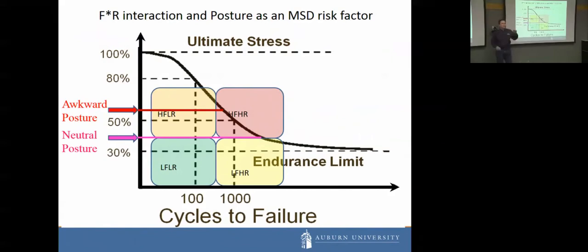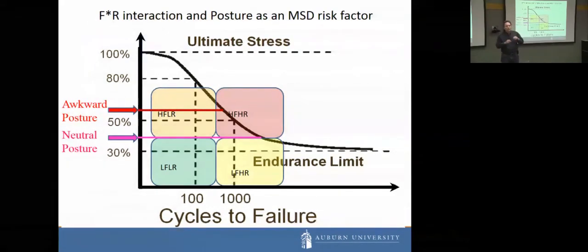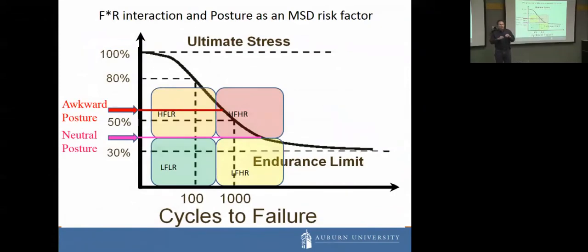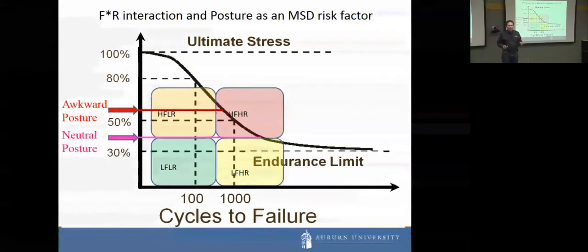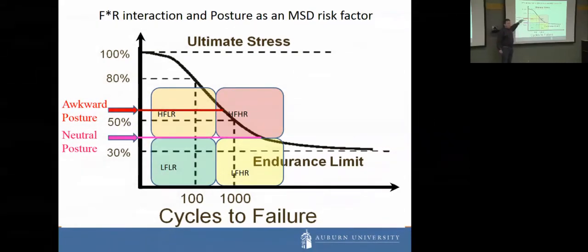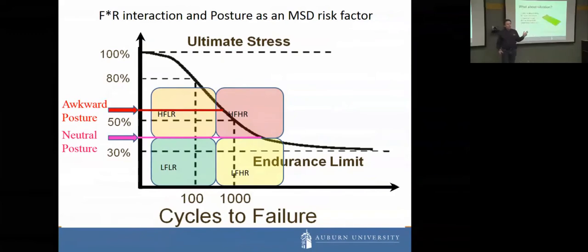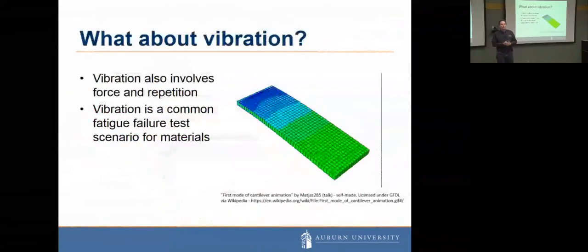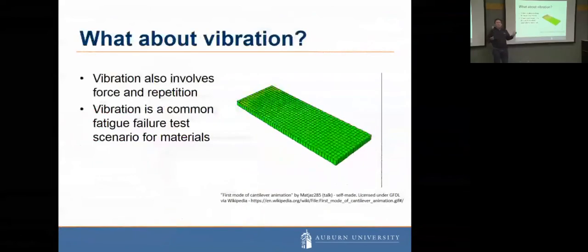Awkward postures can also cause situations like in your wrist, if you're rubbing your tendons along your flexor retinaculum and so forth, you could get a friction going there and potentially some fretting fatigue. So usually when you adopt a non-neutral posture, you are increasing stress on the body in some way. When in a neutral posture, you're generally in pretty good shape and limiting your loads, but when you're adopting awkward postures, you're seeing an increase in this. So that's another risk factor that we think is part of this overall paradigm of fatigue failure.